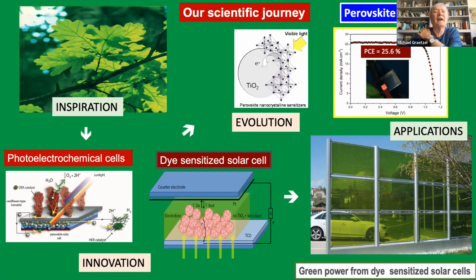But really what took off at the same time is the dye-sensitized solar cell based on sensitization of mesoscopic titanium oxide. Titanium oxide is a large bandgap semiconductor, and everybody tried to shift the light response into the visible, and so did we. And so we used sensitization, which at the time when we started was decried as being a hopeless enterprise.